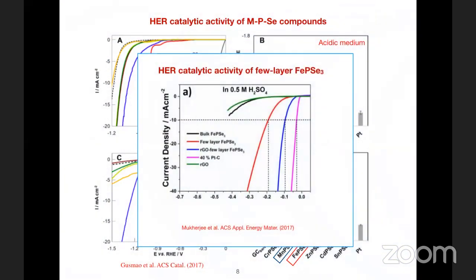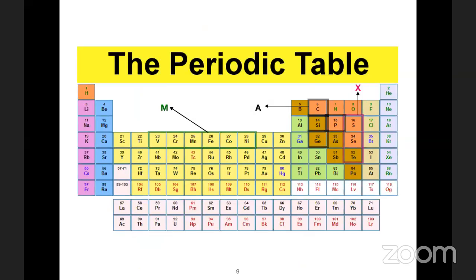So more recently, experiments were done. This is from a group in IISc, Professor Sampath's lab. And here also they show that few layers of FePSe3 or FePSe3 on reduced graphene oxide also act as good catalysts in hydrogen evolution reaction. So that's good news. But what we asked is that only 13 of these compounds are reported in ICSD in the layered structure.